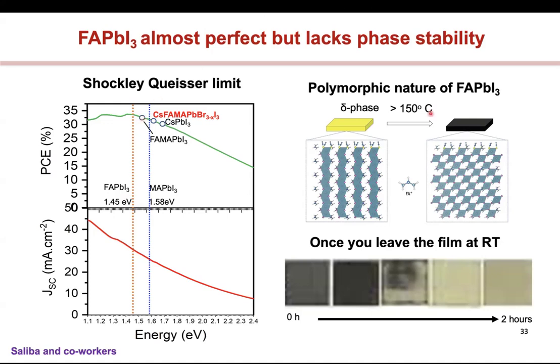Okay. But as I also mentioned, there is this issue where at room temperature it exists in this yellow phase, right? Which is this type of a layered structure. And these are not corner sharing, but these are sort of edge sharing or face sharing octahedra. And so it only turns to its black phase, which is the photoactive phase or the perovskite phase, when you heat this to 150 degrees C, and it undergoes a phase transition and you can get this black phase. Okay.